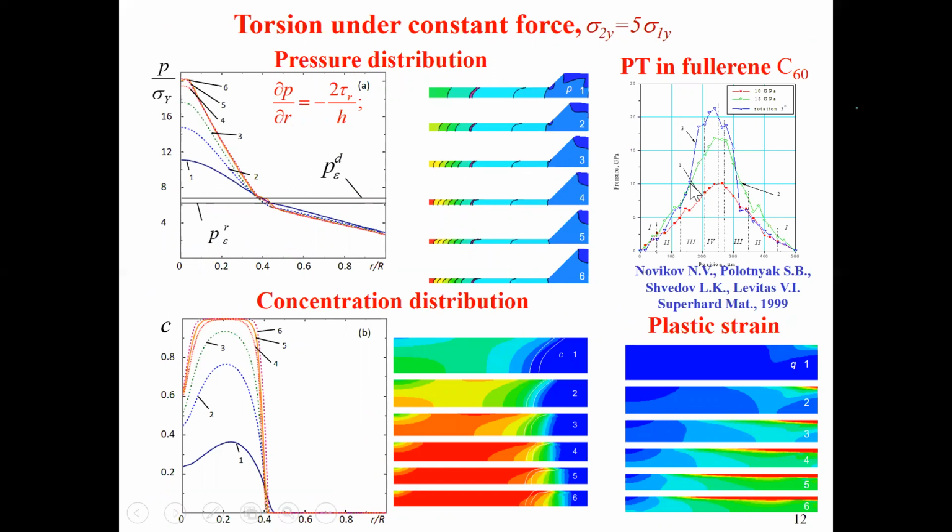So you see here the experiment for fullerite. This is before phase transition to fullerite and rotation. And this is the pressure distribution after rotation and phase transition. Force is fixed. Volume reduces by 35%. So everyone would expect a reduction in pressure. But you see pressure grows.